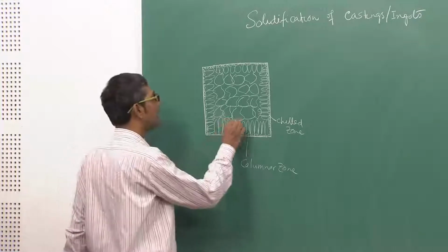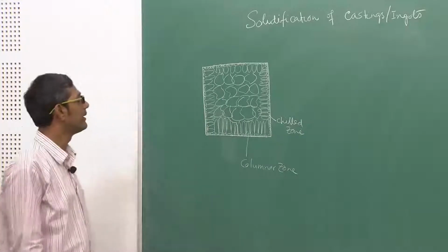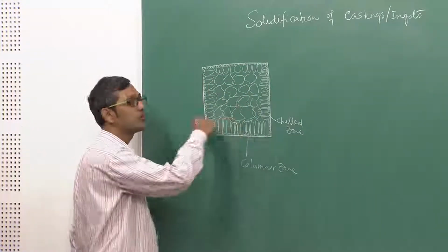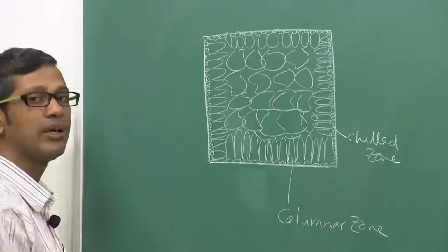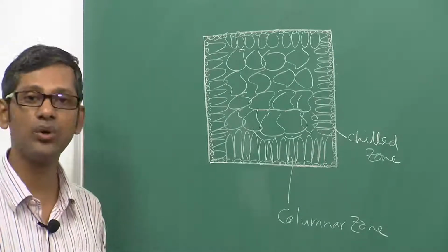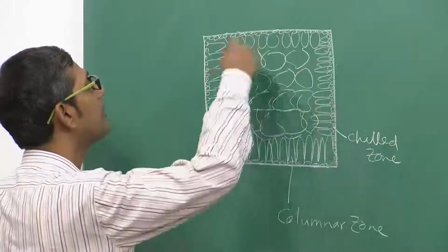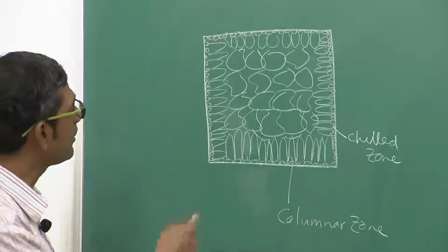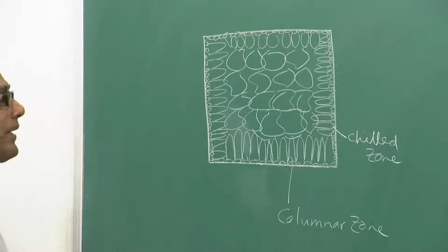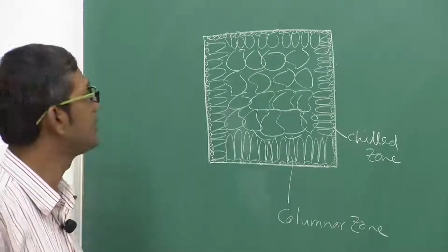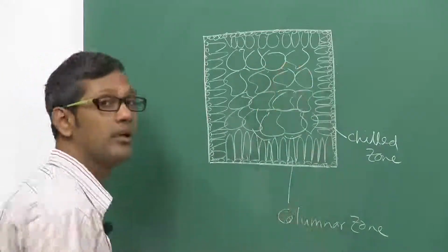As you know, as the liquid solidifies, a lot of solute will be rejected into the liquid. Because of solute rejection, the constitutional undercooling present in the central part of the ingot will be very large, and this constitutional undercooling will allow the equiaxed grains to grow. They do not have any problem with nucleation. Why? Because of the fluid flow present in the liquid, there is a chance that some of the dendrites, or the top part of the columnar dendrites, will break away and reach the central part of the ingot, and then they will start the growth of these equiaxed crystals into the liquid.